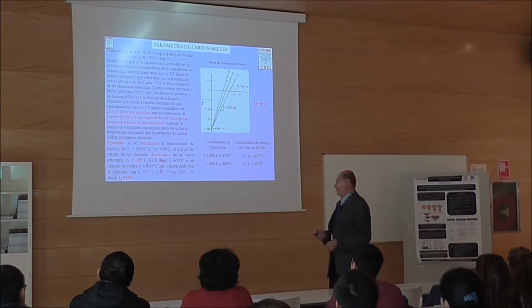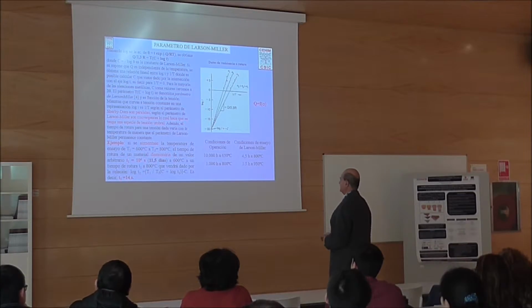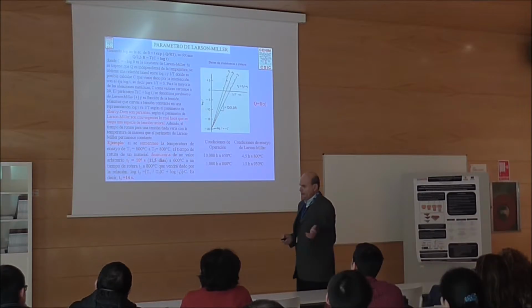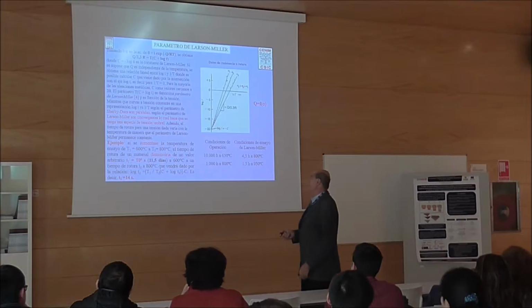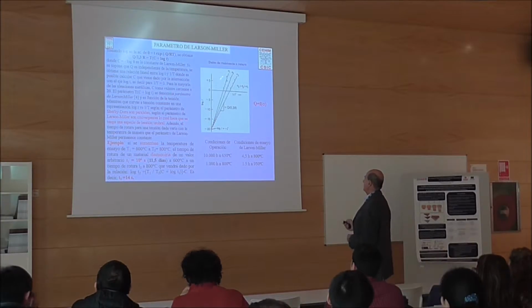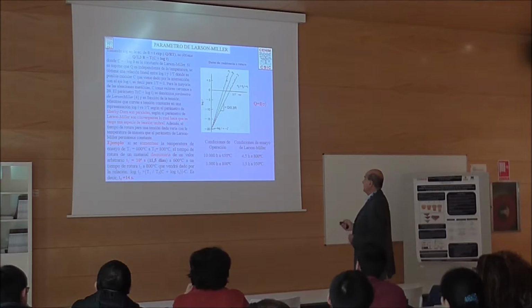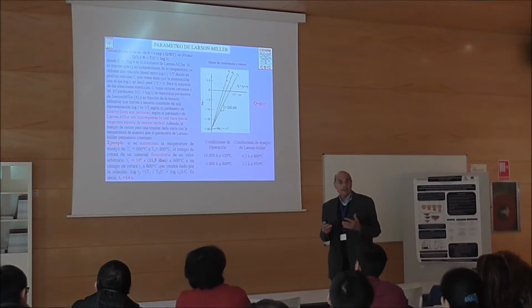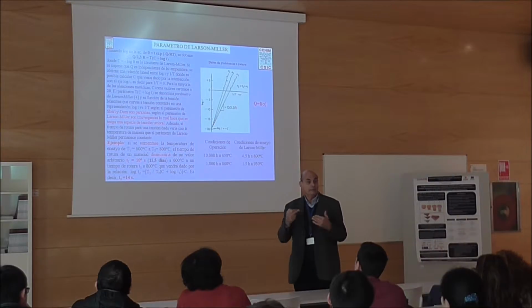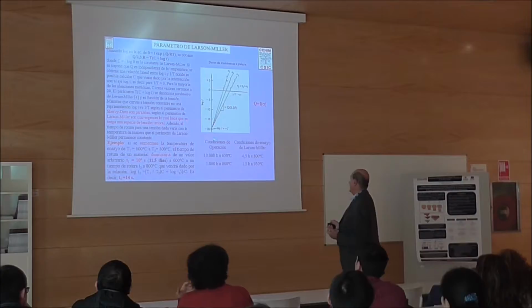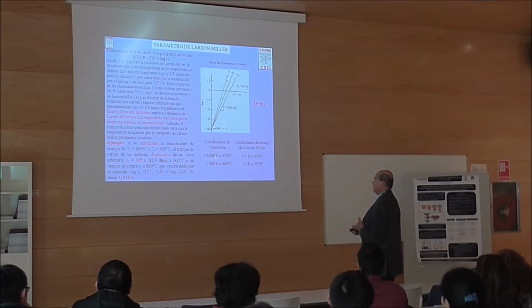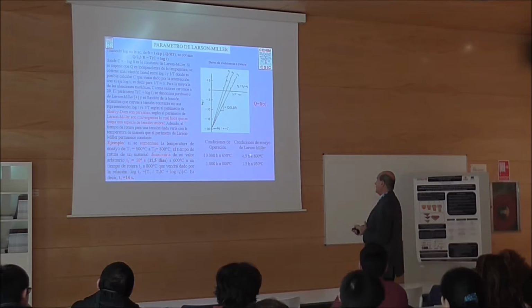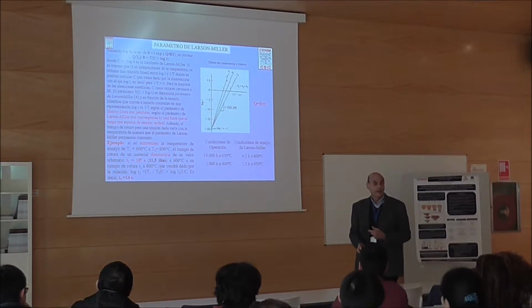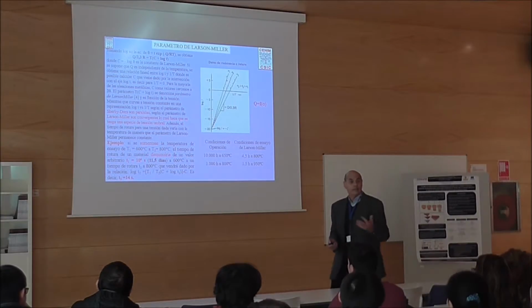Another and very famous prediction, I'm not going into detail. This is the Larson-Miller parameter. You will see a lot of papers and a lot of especially introduction books on creep, where you have this Larson-Miller parameter determination, and this is just to predict the lifetime of a component if you change the temperature. For instance, if you want to wait 10,000 hours, which is a lot of money, a lot of time, at 650, what you do is you go to 800 and you use only 4.5 hours. And you should have the same result.